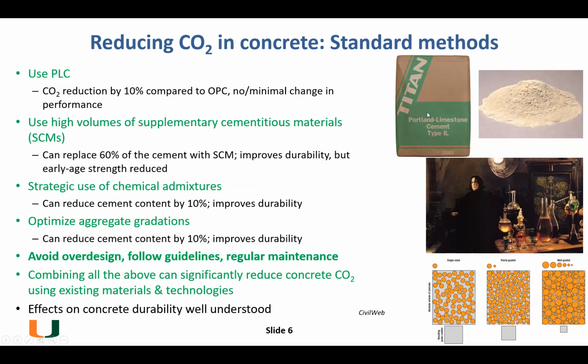Some of these include, as we mentioned, use of PLC, which is Portland limestone cement. So just replacing 5 to 15% of the clinker with limestone instead of heating it up. If you add it at the end, that reduces emissions by about 10%. There's really no change in performance.